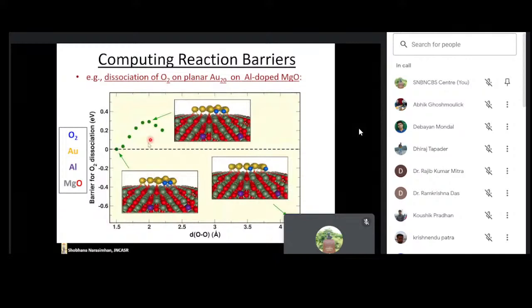So in DFT, we can also compute barriers for certain reactions. So for example, here the reaction that is being computed is the dissociation of this oxygen molecule, which is shown here in blue. You can see that the two oxygen atoms are slowly coming further and further apart, and finally the molecule is dissociating, and you can compute the energy barrier for this.